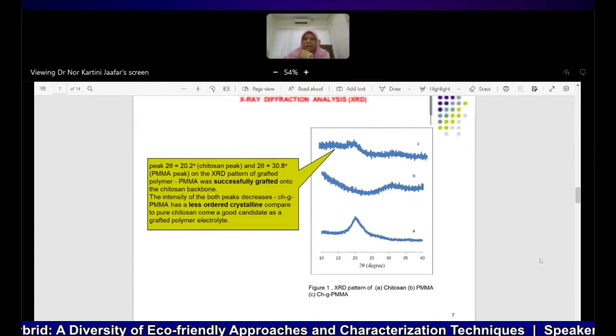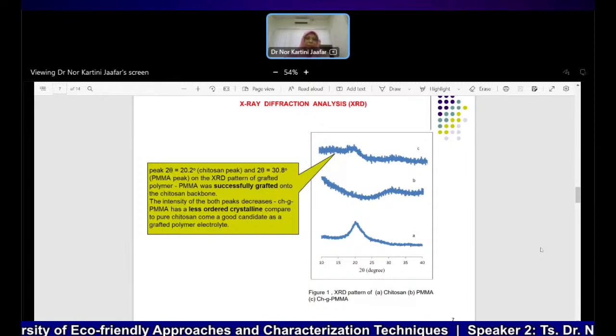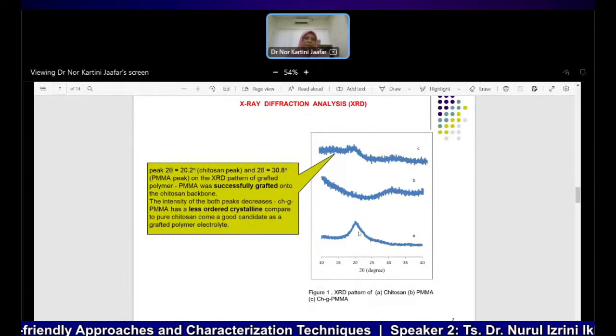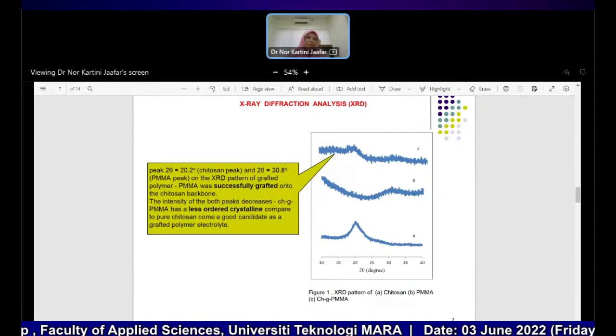This is the XRD spectrum for the grafted polymer, comparing the spectrum of pure Chitosan, pure PMMA, and after grafting, where both peaks of Chitosan and PMMA appear in the spectrum. From this we conclude that PMMA was successfully grafted onto the Chitosan backbone. We can also see the Chitosan peak slightly reduced, suggesting the crystallinity of Chitosan is a little reduced.